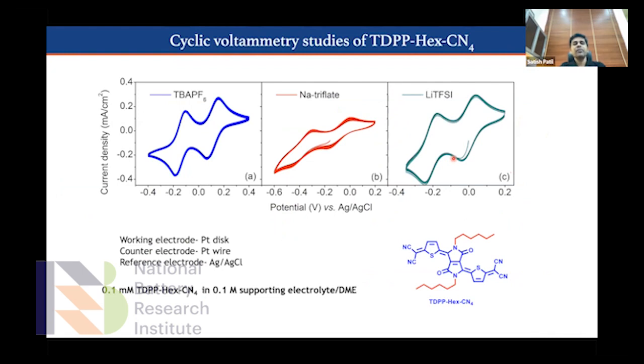Here again, we used a different salt. It's important to see which is giving the best results. This is basic fundamental science. One has to screen out a different class of salt. For example, TBAPF6 shows a very reversible CV. When you go to sodium triflate, this did not show very reversible behavior, whereas lithium TFSI indeed shows very reversible behavior. What this essentially tells me is that there is a sort of ion dependence. You see that the electrochemical behavior of this particular material depends upon what kind of salts you deploy to do a redox reaction.